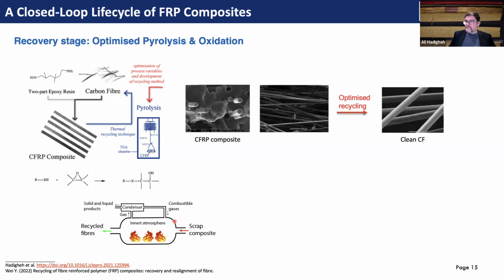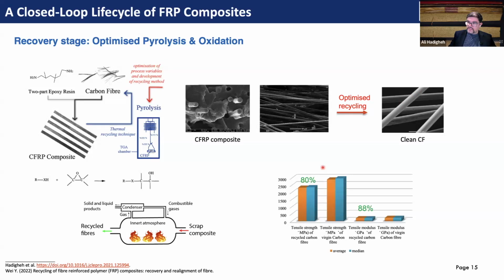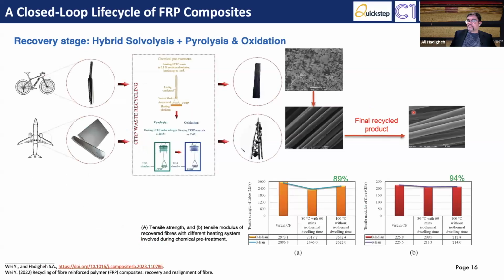With that, we had these CFRP composites, and after recycling, we could get clean carbon fiber from the composites, of very good, high quality, with around 80% of tensile strength retention and 88% of tensile modulus retention, which is quite reasonable, and with minimum energy usage. But the challenge was that if you look at that in more detail, you see some discontinuity on the surface of carbon fiber that relates mainly to the temperature that we use. So we tried to optimize that, but after certain temperature, carbon fiber will get damaged. So we took that further.